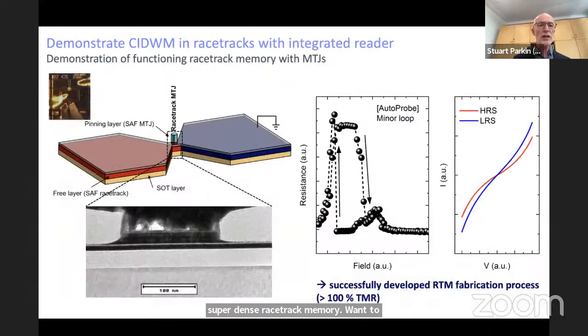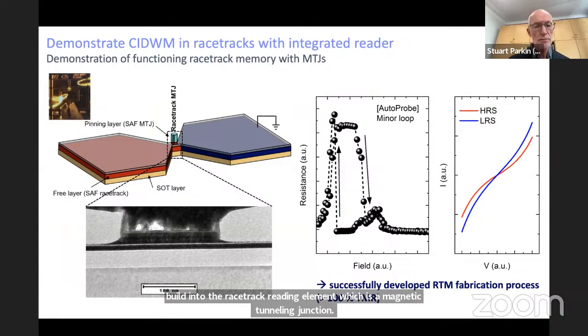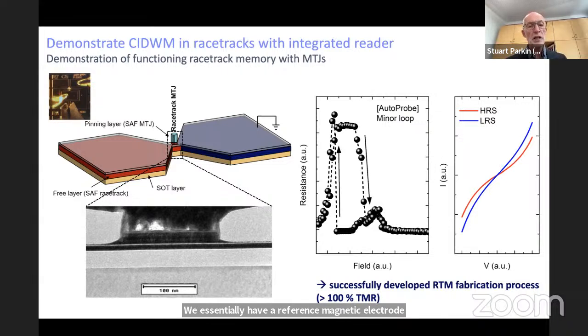I want to just mention one other final point without going into any details. I mentioned earlier that for the racetrack, we need a reading element, so we can build into the racetrack a reading element, which is a magnetic tunneling junction. We essentially have a reference magnetic electrode formed from a synthetic antiferromagnetic layer itself, which is above the racetrack, separated by a thin magnesium oxide tunnel barrier layer.